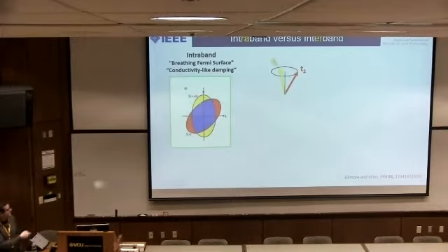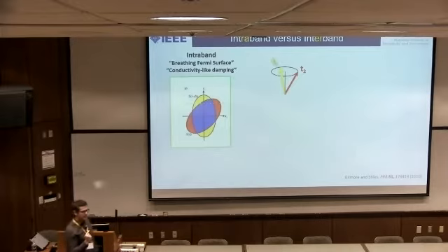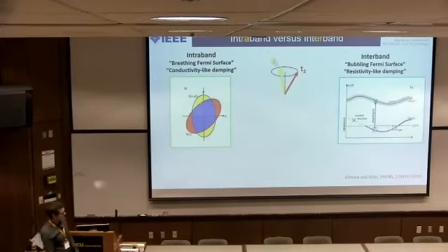The problem is that all of these spins that were at or below the Fermi surface at time 1, in yellow here, are now above the Fermi surface at time 2. And so we have to constantly be scattering and repopulating that Fermi surface to maintain equilibrium. And it's that scattering process that gives rise to this damping.